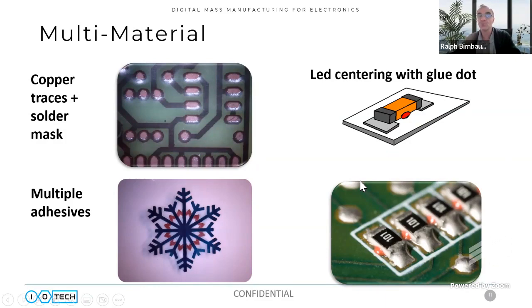And on the right is an application with 2 very different materials. So this is a LED centering application with a glue dot in the middle, used especially in automotive headlights to make sure that all the LEDs are perfectly 100% aligned. A small epoxy dot is placed in the middle. So with this technology, you can print the solder paste and the epoxy dot using the same machine. No handling would be required, no moving to another machine. Everything is done in one station.